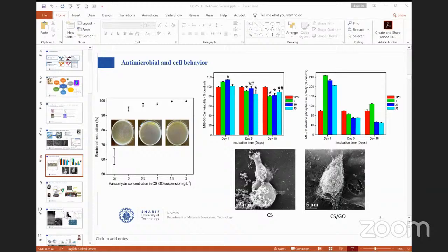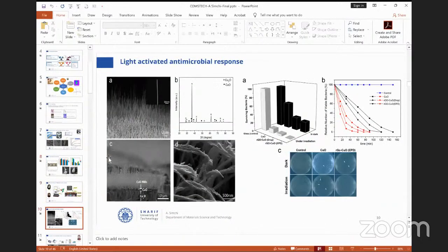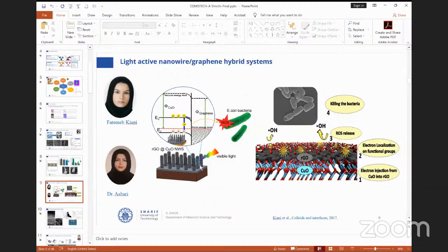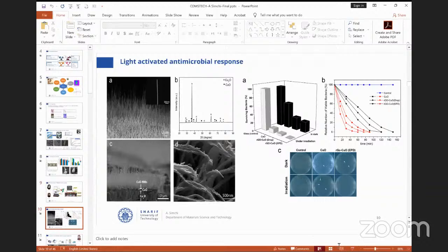In the next run, we tried to develop antibacterial surfaces by combining nanorods and graphene oxide layers to make them light active. So when the light hits the surface, especially the functional groups of graphene oxide, it creates functional groups that can stick to the bacteria and kill them. To do so, we used, I am on slide 10 now, a procedure we developed to grow well-aligned nanorods of copper oxide.